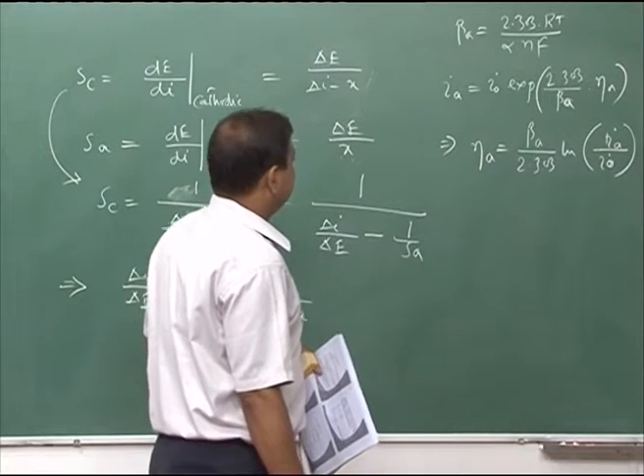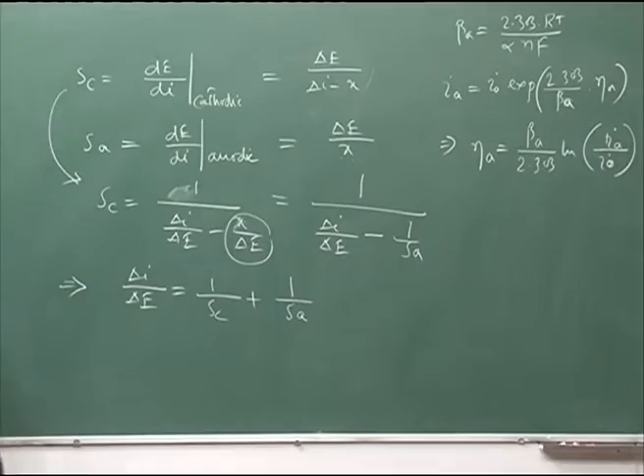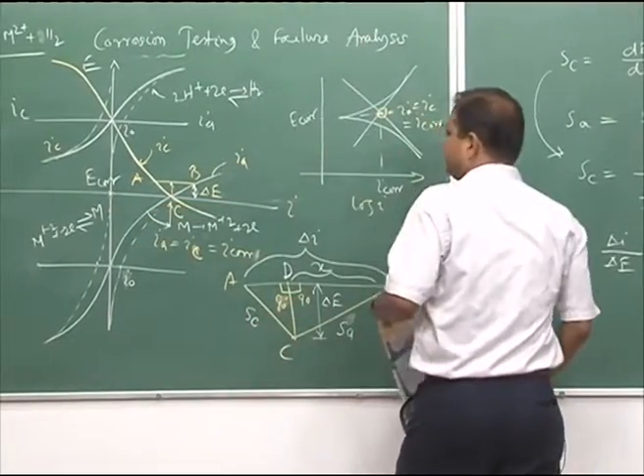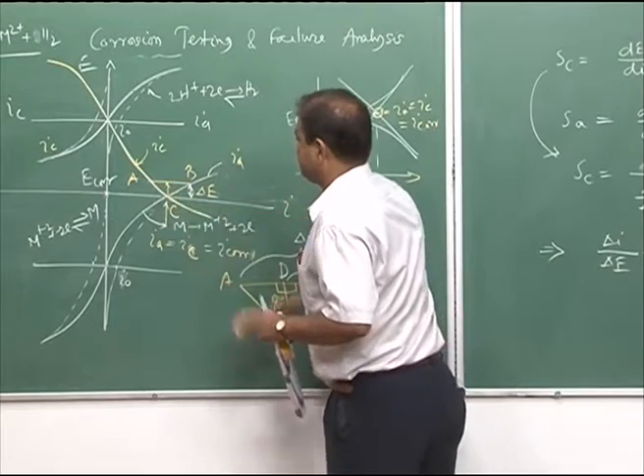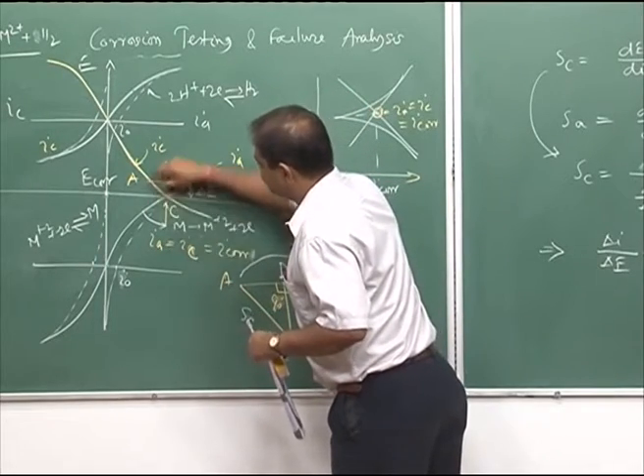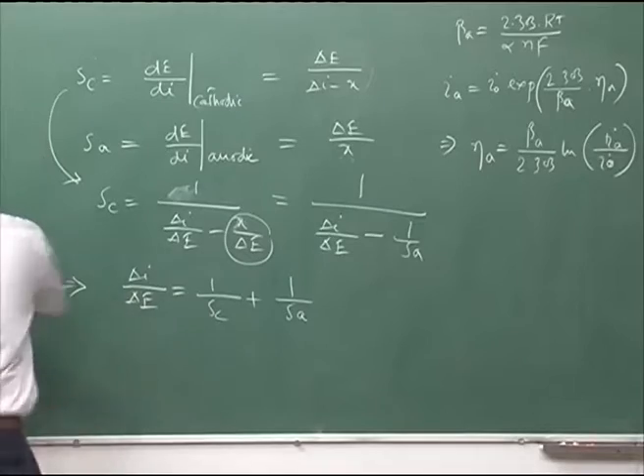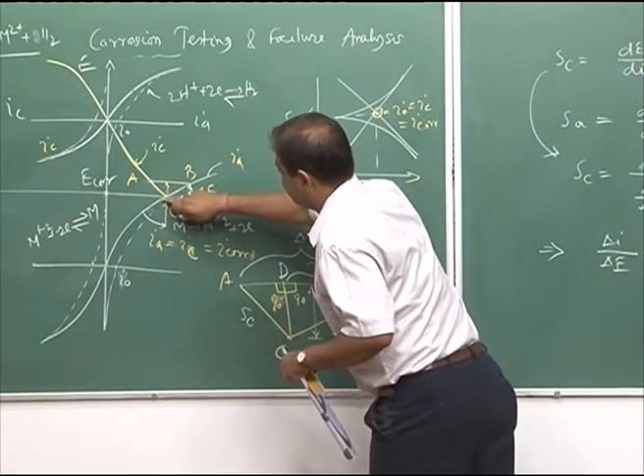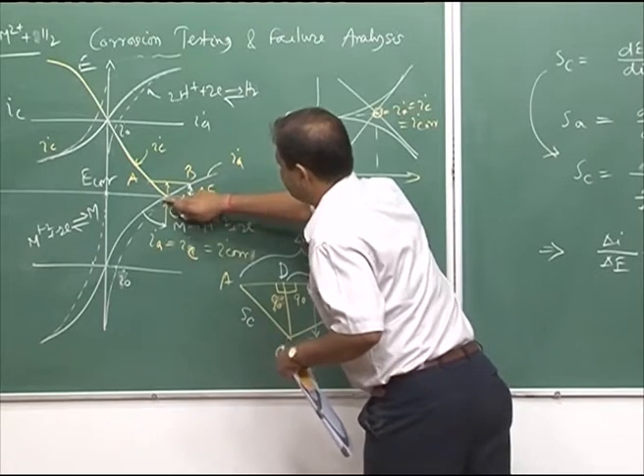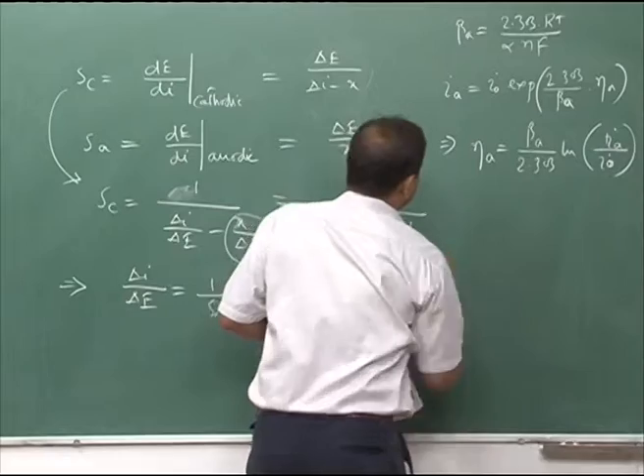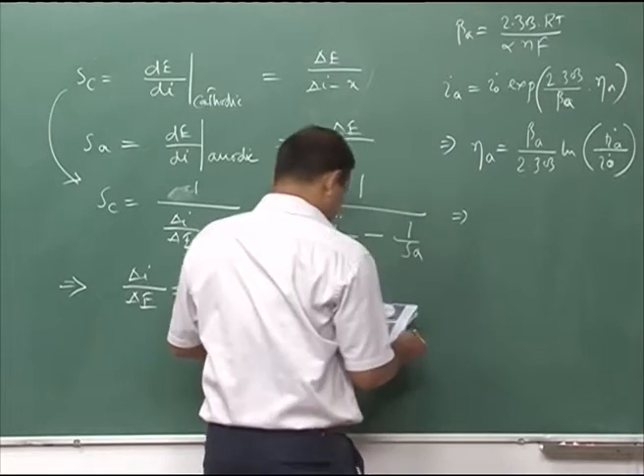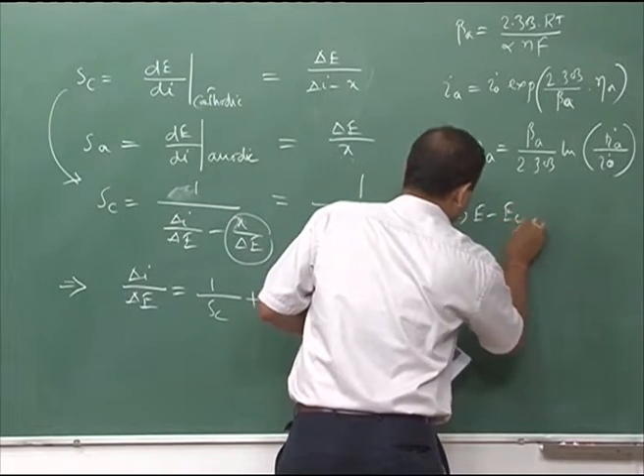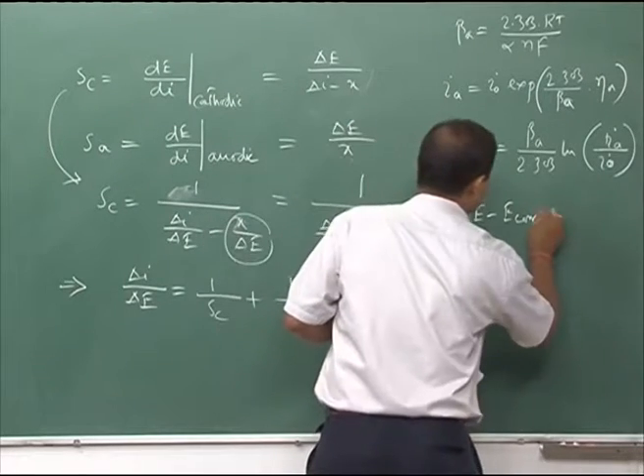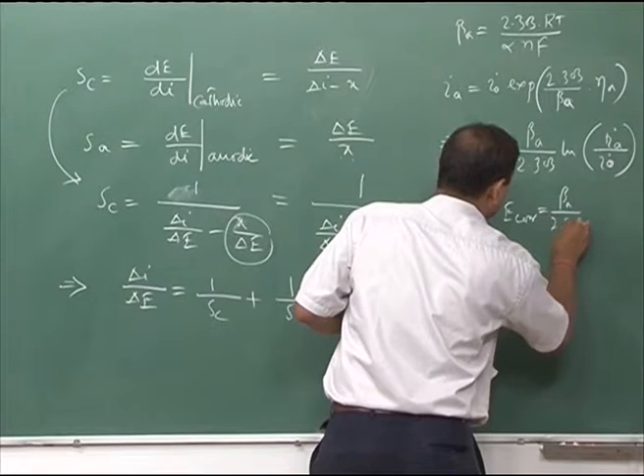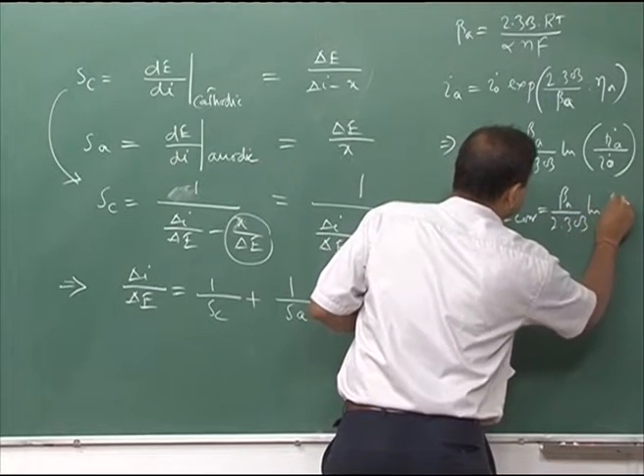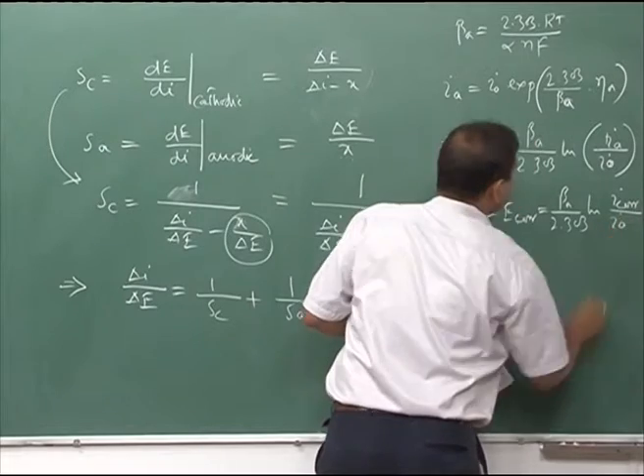And at corrosion potential, that means if we come to this point at corrosion potential, if we would like to find out what is the slope at this point, and that actually passes through this small linear part, or if we consider this anodic side, that time the slope would be passing through this point, which is at E corr. So, neta at a small over voltage, this we can write as E minus E corr would be equal to beta A 2.303 ln I corr by I 0.